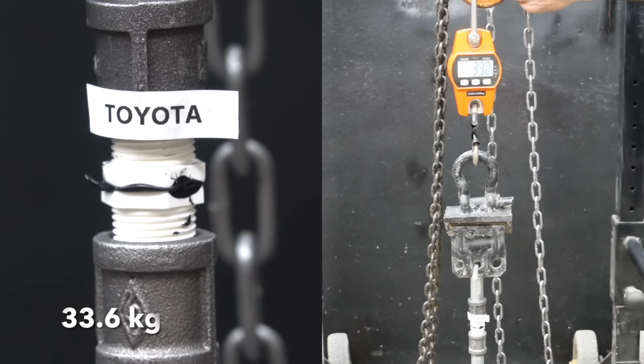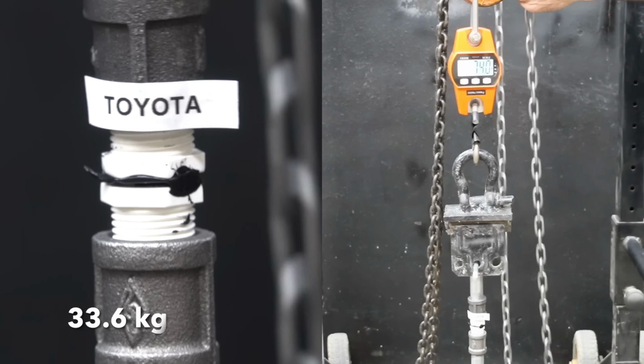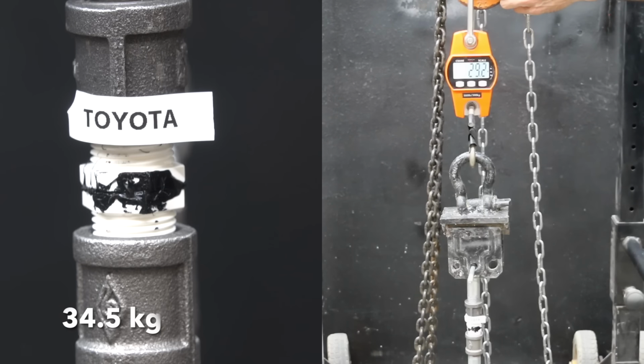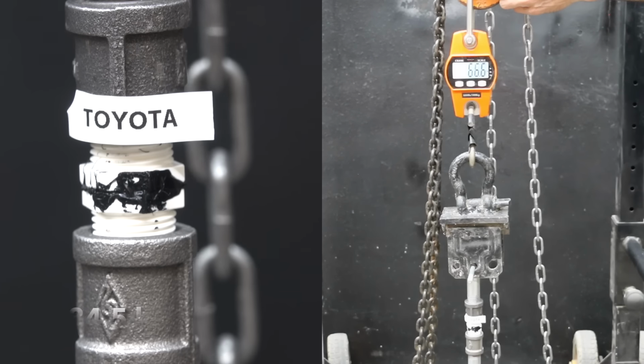And the Toyota performed even better on the second test piece at 74 pounds. 76 pounds on the third test piece, for a very consistent performance by the Toyota brand.